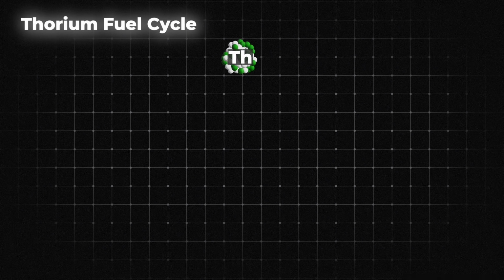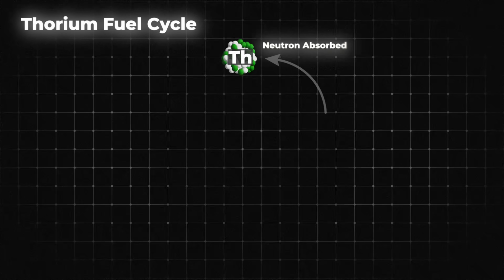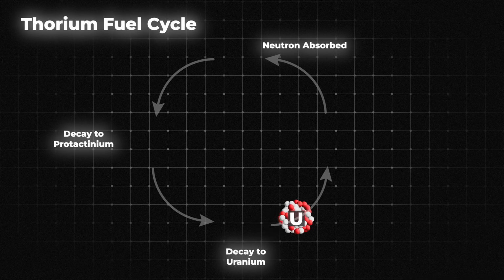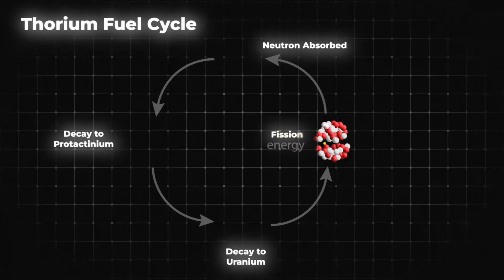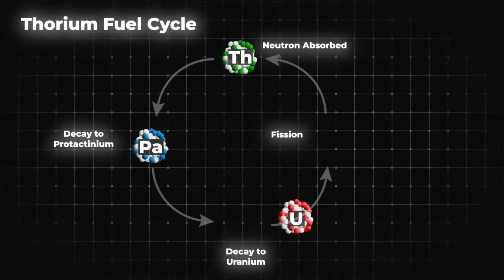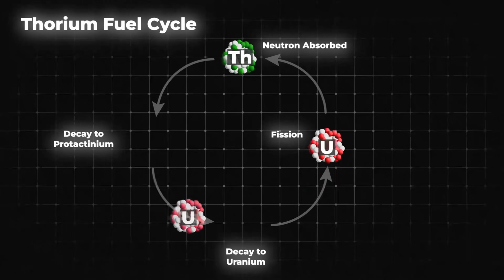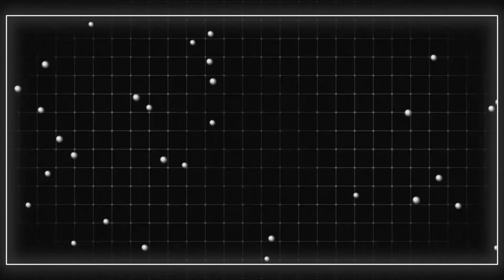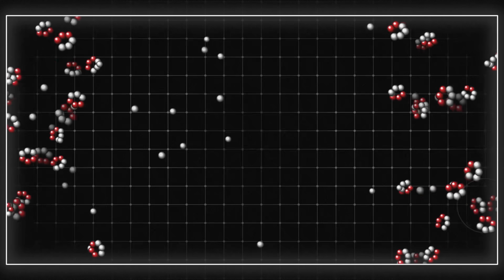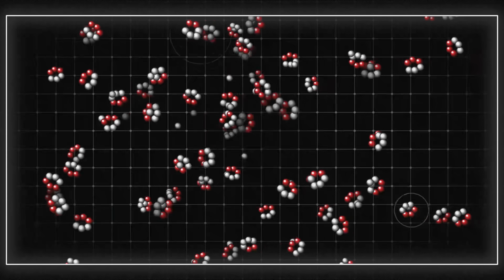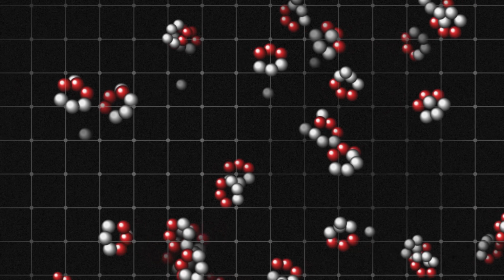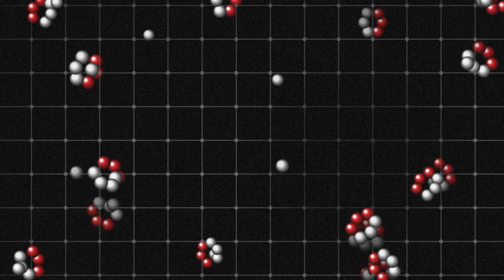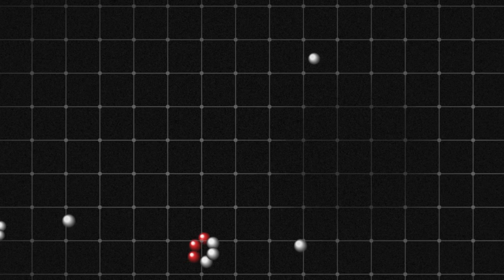But with thorium, things are different. Thorium itself isn't fissile. When you hit it with a neutron, it turns into uranium-233, which is not only fissile, but much more energy efficient than uranium-235. That's the actual fuel that generates the power and the 2.5 neutrons. So in this case, you need one neutron to split uranium-233 and generate power, and one spare neutron to breed more uranium from the thorium fuel. If you have lithium-6 around, it'll suck up all the spare neutrons and kill the reaction like tossing water over a campfire. But lithium-7 is completely transparent to neutrons. It's 20,000 times less likely to absorb a neutron than lithium-6.